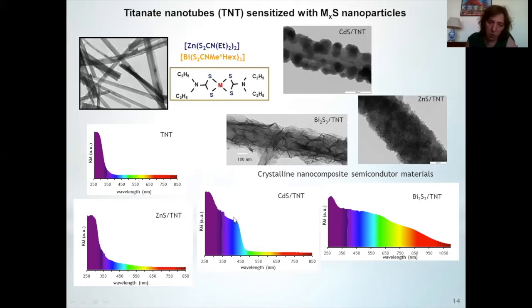We can see the absorption of the CdS particles and also the absorption of the naked surface of the titanates. In the case of zinc sulfide, well, if we compare it with the absorption of titanate nanotubes, they are more or less similar, but I must say that this combination is excellent when we are interested in reducing the recombination rate of the charge carriers. So that's why we use zinc sulfide nanoparticles a lot.